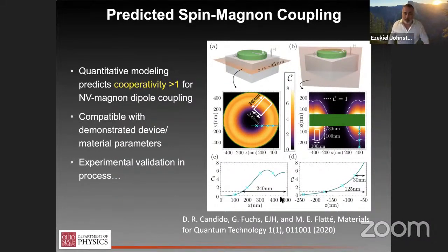And this dotted line is at a cooperativity of 1, which as a function of depth, you can see, down to 125 nanometers, which is quite deep into the diamond, so you're well isolated from the effective surface spins, you surpass this cooperativity threshold. This X cut is just moving across the disk. So if the edge of the disk is, say, here, 240 nanometers beyond that edge, you'll still have a pretty high cooperativity. So what this means is that the magnons in YIG are sufficiently coherent that if we can build a structure like this, we should be able to use it to read and write quantum information to an NV center.